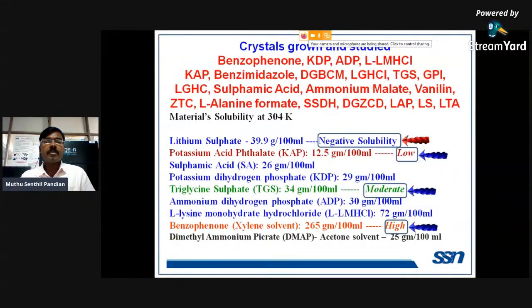So far, by this method, more than 250 crystals have been grown. We can grow low soluble crystals like potassium acid phthalate, and moderate solubility crystals like TGS. We can grow highly soluble crystals like benzophenone single crystals. You see, 12.5 gram per 100 ml is a low soluble material, 34 gram per 100 ml is moderately soluble, and 265 gram per 100 ml is very highly soluble.